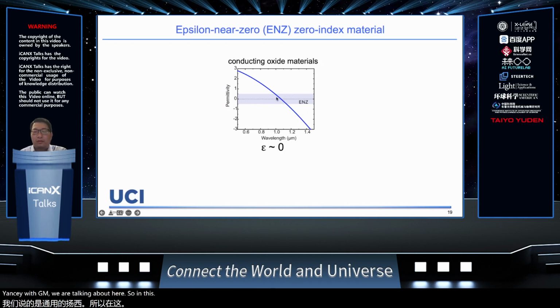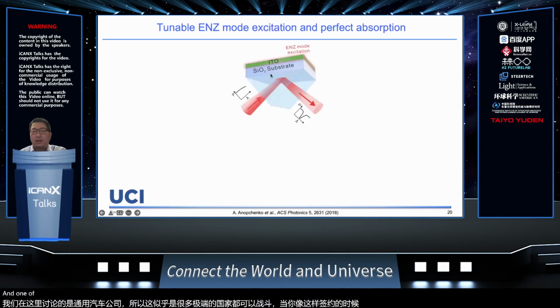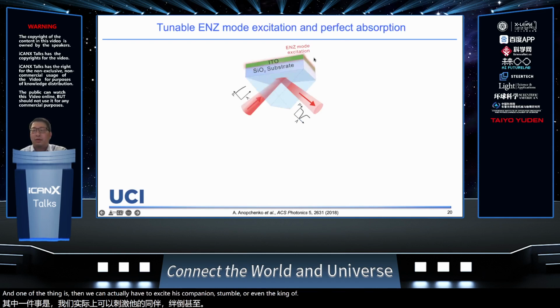So in this regime, there are a lot of extreme optics and physics we can find when you shine light on this. One of the things is that you can actually excite this ENZ mode, or even make it a perfect absorption property. Basically, it's quite simple. You just have a thin layer of this ENZ material. In this case, we have an ITO material. By shining the light at a certain angle, you'll be able to excite this so-called ENZ mode.